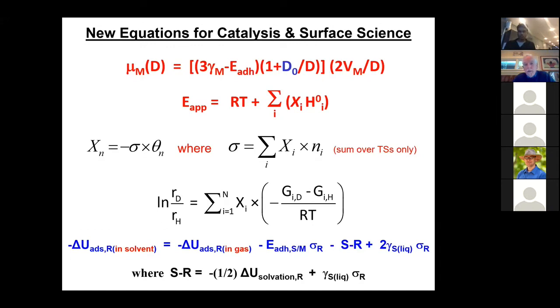That's why the surface energy goes up, and you would get that if you just had some dumb calculation of surface energy using some kind of a dumb Lennard-Jones potential for metal-metal interaction and a pairwise bond additivity there. And you can kind of get the same thing for adhesion energy effects. It's harder there to think about how to do that with pairwise bond additivity.